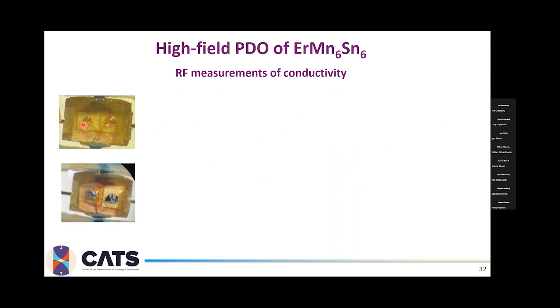We can see here the PDO coil, on top of which we put the erbium manganese six tin six crystal. That technique is sensitive to changes in skin depth. Therefore, it will give us information about changes in the conductivity when we talk about metals or superconductors. The interesting part is that for some materials which are semi-metals or insulators, it will also be sensitive to picking up changes of the magnetic moment in that compound. And as we know, since erbium manganese six tin six has a very complex magnetic structure, we might also see some influence of that.